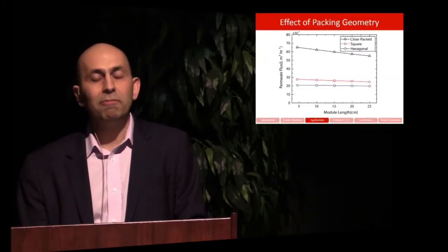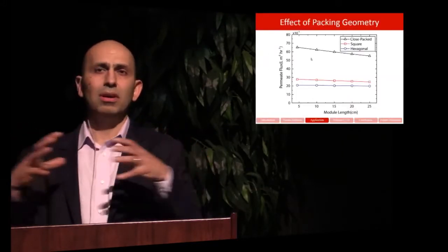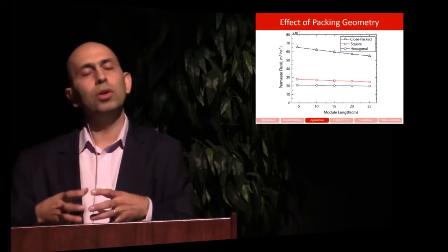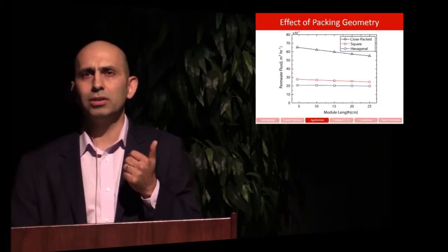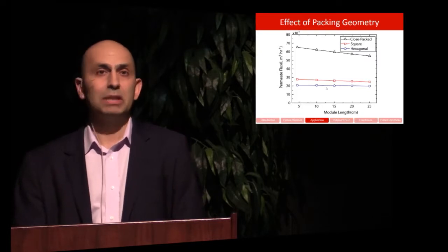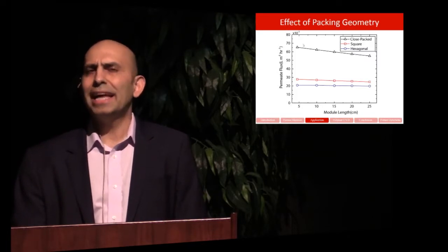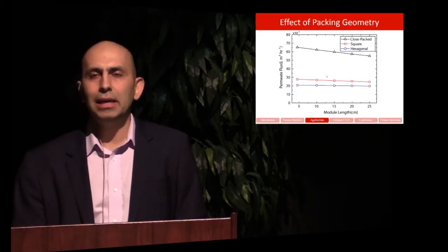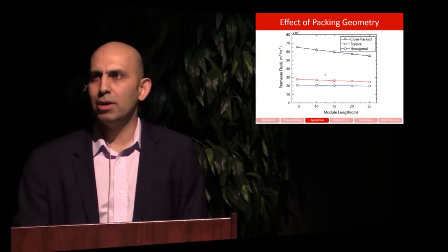So here's the initial result we had. I'm going to tell you exactly what they are in a second. But what I want you to pay attention to is that we look at the permeation flux as a function of different properties of the module that we designed. Here's the first one, effect of packing. As you know, if we pack more membrane in less volume, we should get more flux. This is expected, and we do see that. There's an additional effect in here that is hidden, and that's the thermal efficiency of the process.